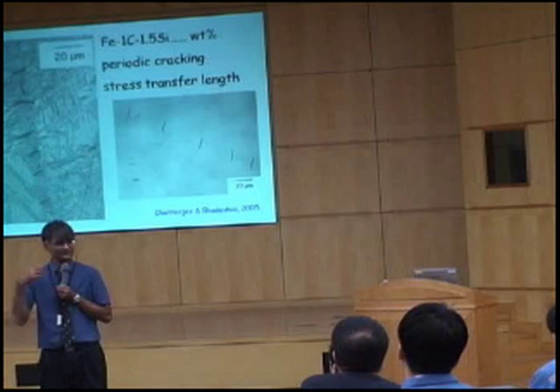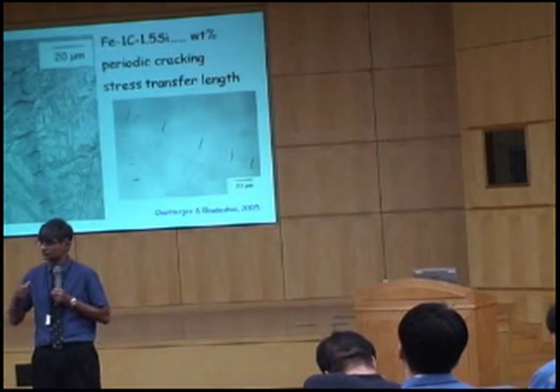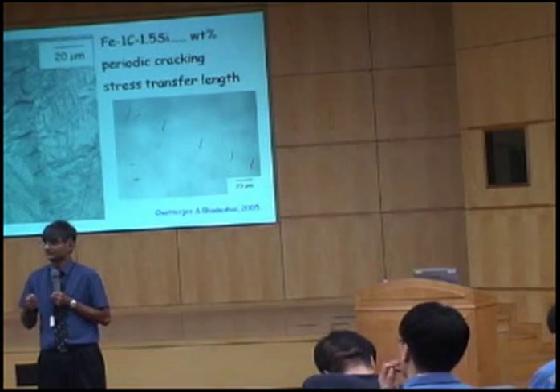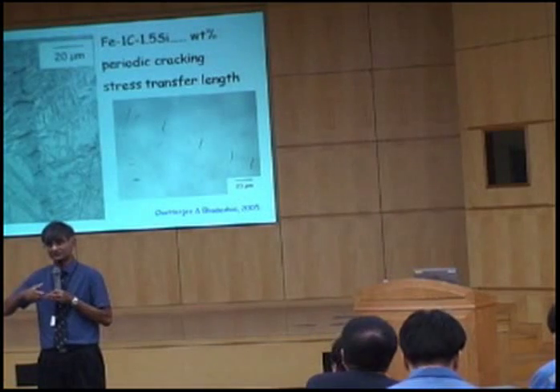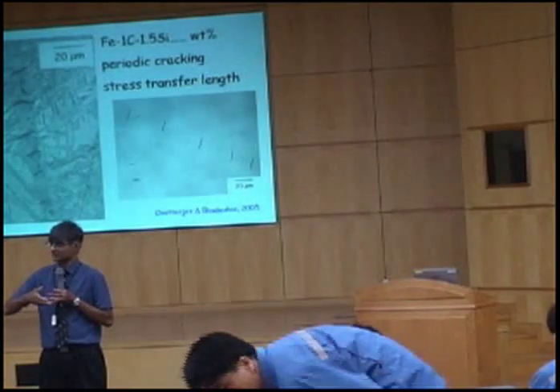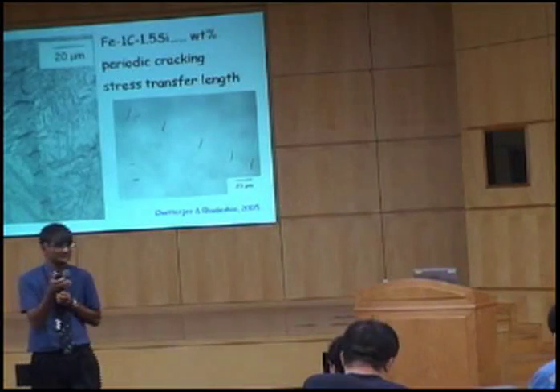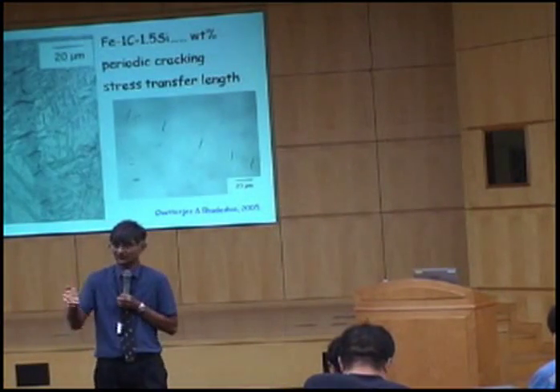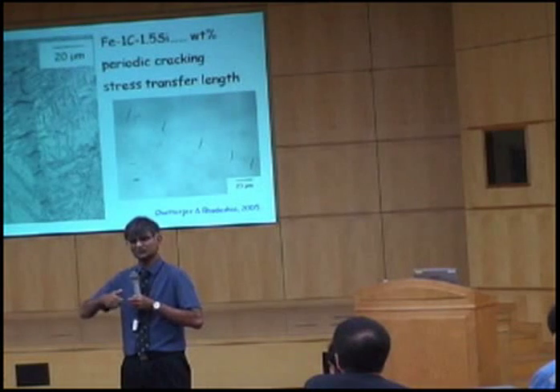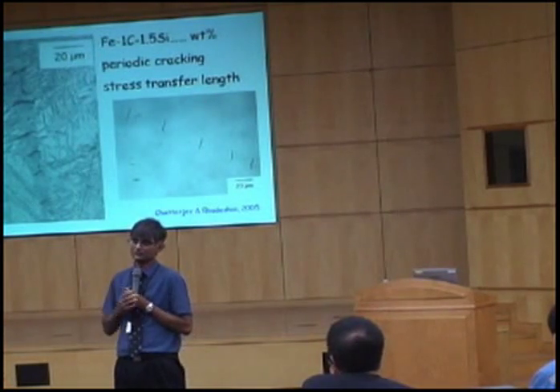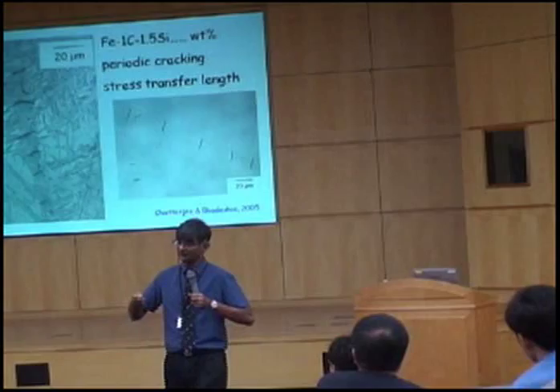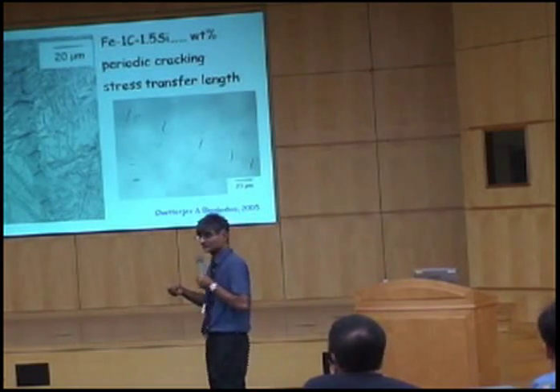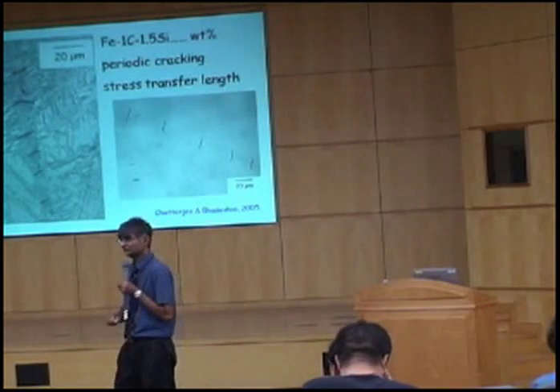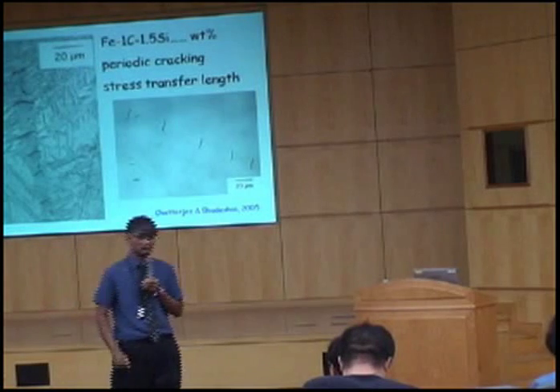So there's not a single answer. It depends on how strong your steel is. If it is not a very strong steel, then it's difficult to transfer stress onto the martensite, and there's not a problem. Like, for example, the TRIP-assisted steels that you have in cars. Those are strong, but not very strong in the context of strong steels. But if you're making something which is 2.5 gigapascals strong, then you've got to make your islands of austenite much, much smaller.